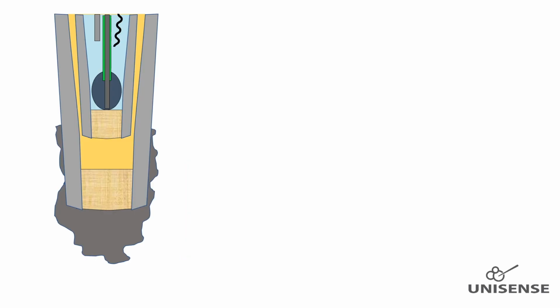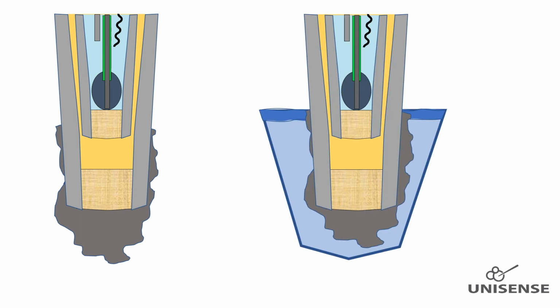If the sensor tip gets biofouled or covered with sticky polymers, it might measure incorrectly. The tip tolerates almost all possible cleaning substances like alcohol, acids, detergents, proteinase solutions, etc. So it is recommended to insert the sensor into different cleaning solutions to see if this solves the problem as the first attempt to remove the fouling. If chemical cleaning does not remove the fouling and restore normal performance of the sensor, a physical cleaning is the only solution. If you hold the sensor tip so it points away from you, the wipe direction must always be the direction the tip points, never against the tip, which will impose a risk of tip damage.